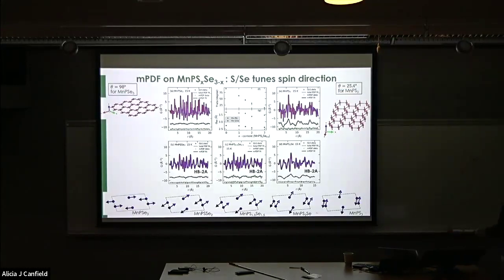Okay, so here we're looking at the whole series again, using the non-traditional PDF instrument where resolution is worse, but you can still fit the data pretty nicely. For Se3, you have a weak magnetic signal that increases as you increase the sulfur content, so the intensity gets bigger and bigger and goes up to the S3 case. What we find fitting this is a very nice gradual tuning of the magnetic moments across the series. So you don't have just an abrupt change somewhere; you're able to finely tune the magnetism. This theta is the angle, where 90 degrees is in the plane, and it starts to move out of the plane. You can almost put a straight line to this, and then it's just showing the manganese distance changing.